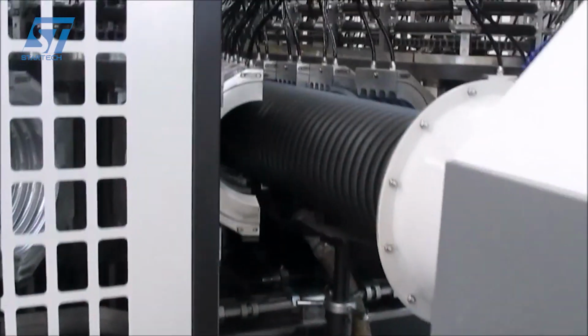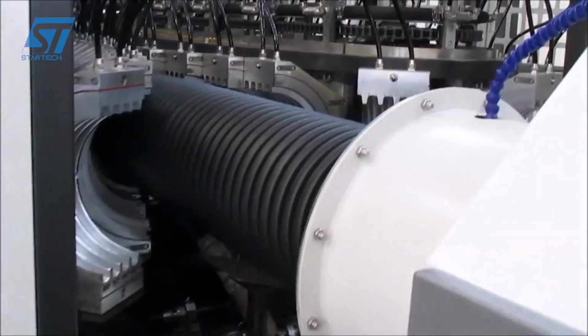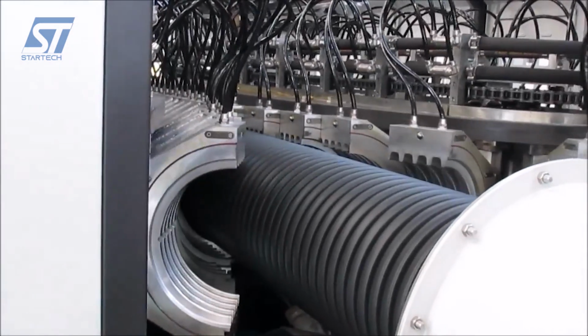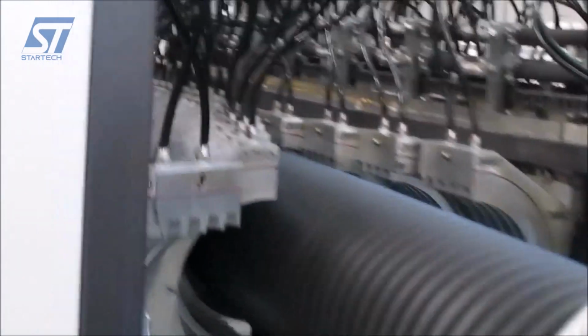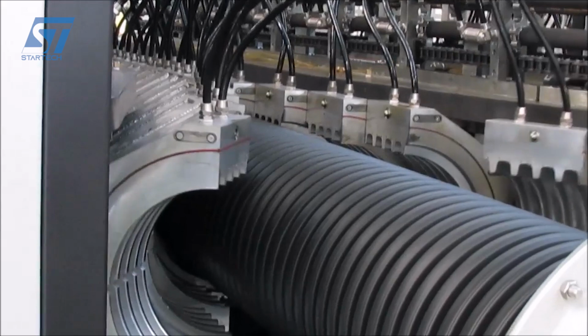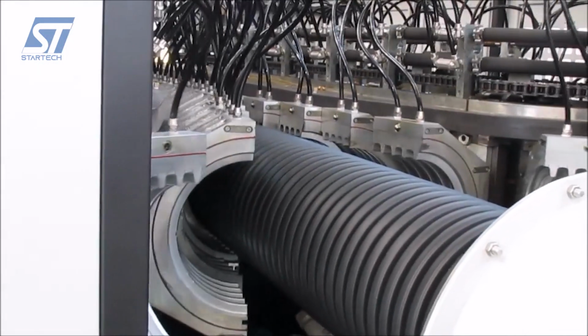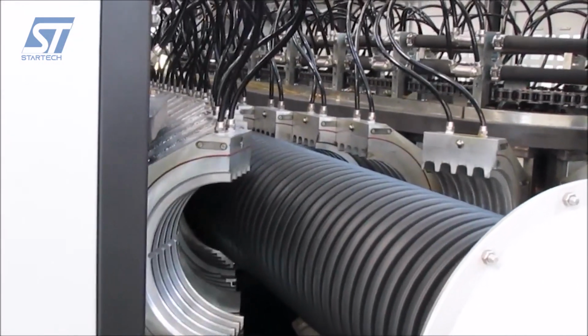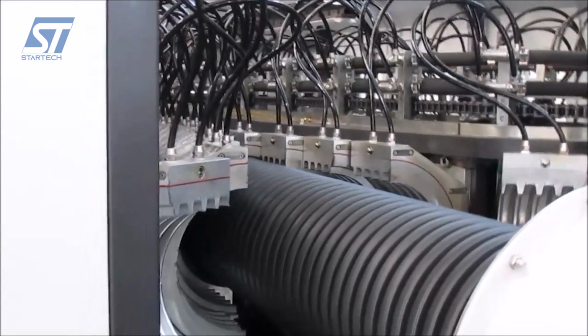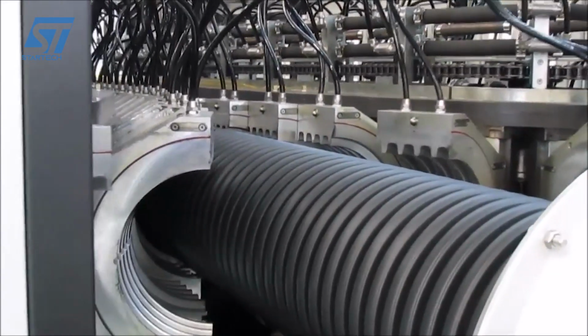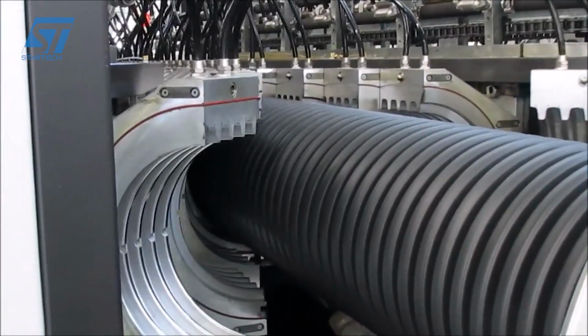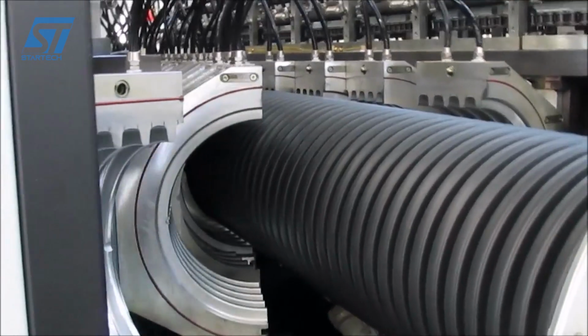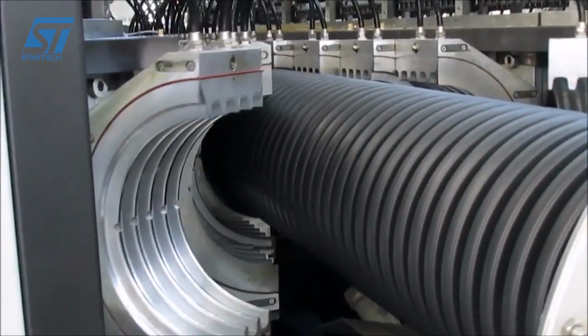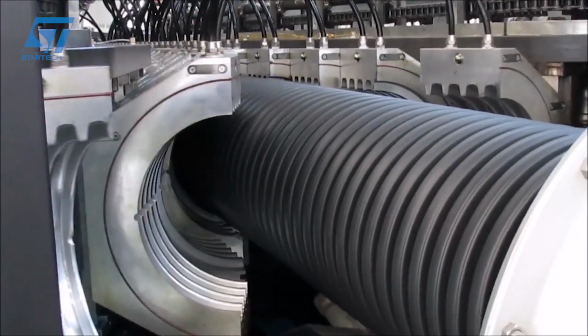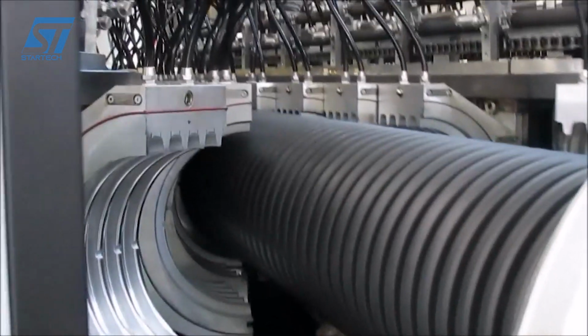Additives such as UV inhibitors, heat stabilizers, and colorants are mixed in precise proportions. The resin and additives are loaded into the hopper and fed automatically. This system ensures that the raw materials are fed into the extruder at a uniform rate. The twin-screw extruder heats and mixes the resin at high temperatures, 180 degrees Celsius to 250 degrees Celsius. The molten resin mixture is forced through the extrusion die to form the basic tube shape.